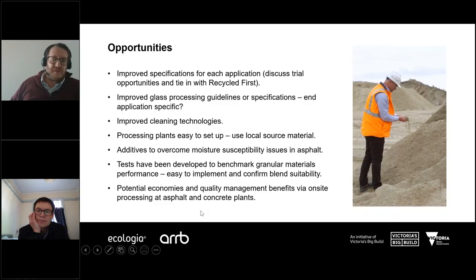In terms of moisture susceptibility, there's a number of additives that could be used to reduce those potential moisture susceptibility issues. So anti-stripping agents, etc. So there's ways to manage some of the potential issues that are seen around recycled crushed glass to make them perform very well in asphalt mixtures, for example.